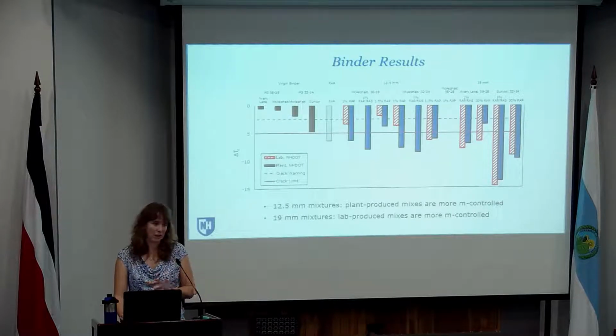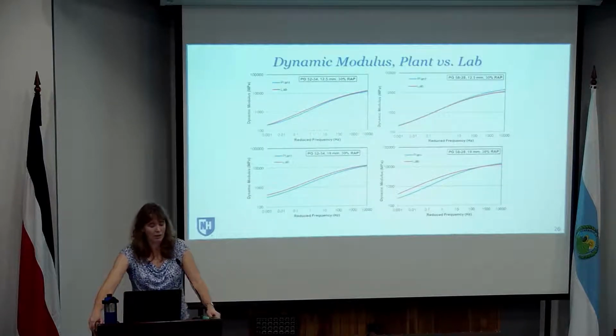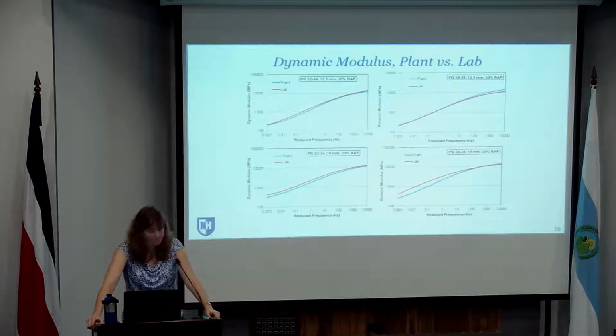Now, because we're dealing with mixtures, we wanted to look at the mixture performance as well. Okay, so this is just an example of some of the dynamic modulus curves, okay, with the plant versus the laboratory. The plant curves are those in blue. Okay, the laboratory produced materials are in red. And you can see for some of the mixtures, there was a relatively big difference. Okay, and this was a statistically significant difference.